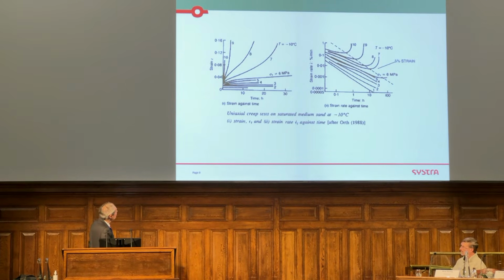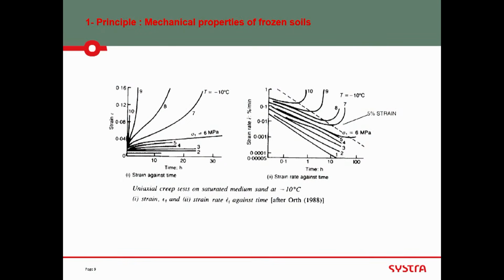Now, if you plot this result into this diagram, so you see the temperature is minus 10, and you take the slope. Okay, so the slope is epsilon dot, the strain velocity. You plot it in this diagram. So horizontally, it's time still, and then this diagram is the slope of each loading case. This is what happened. So the strain velocity, you see that for 1 MPa, the slope is quite constant. Okay, 2, 3, so on.